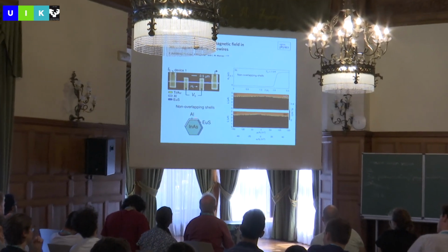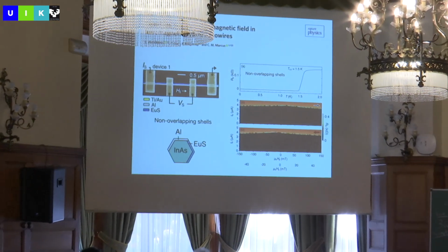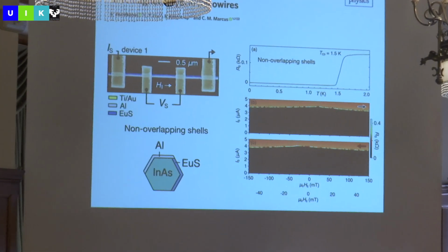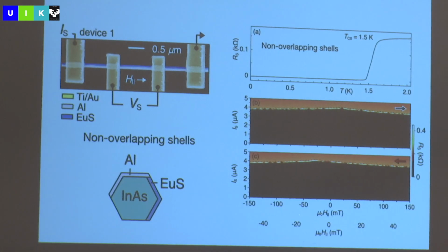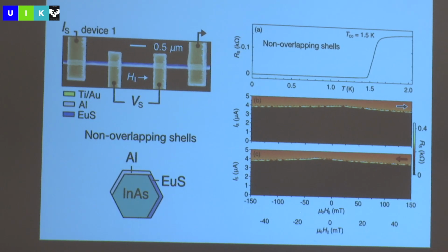Just to show we're not totally crazy, if we grew these in a slightly different orientation, on non-touching interfaces, so now the aluminum is on one side and the europium sulfide is on the other, it does a little bit, but it basically doesn't do very much at all. What this means is that this is not about the europium sulfide affecting the indium arsenide. It really has to touch the aluminum. It's the interface of the europium sulfide and the aluminum, and then that spin-split aluminum proximitizes the nanowire.